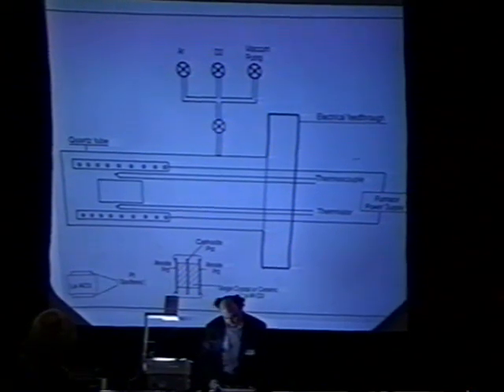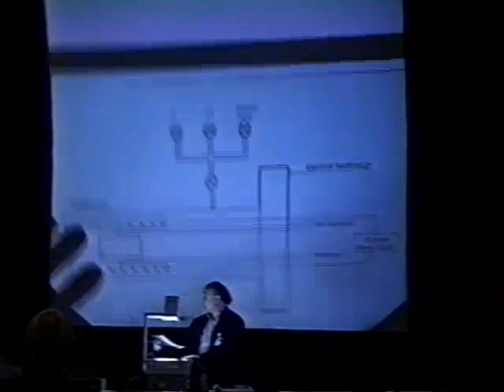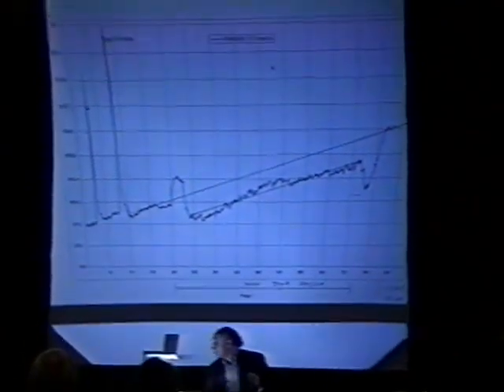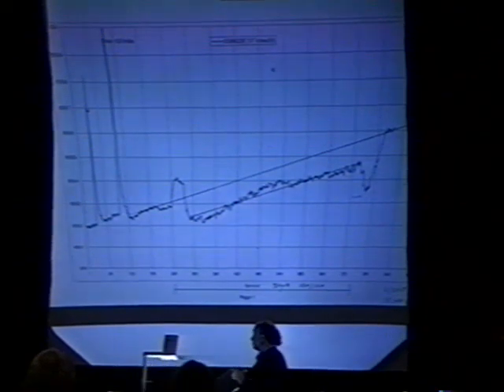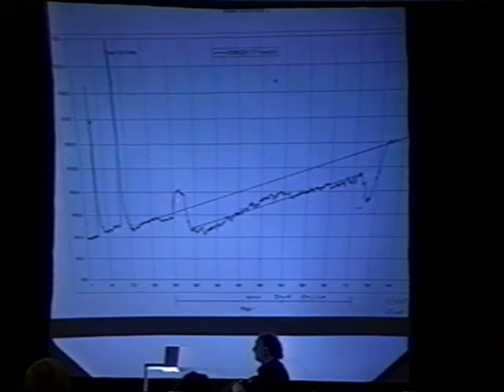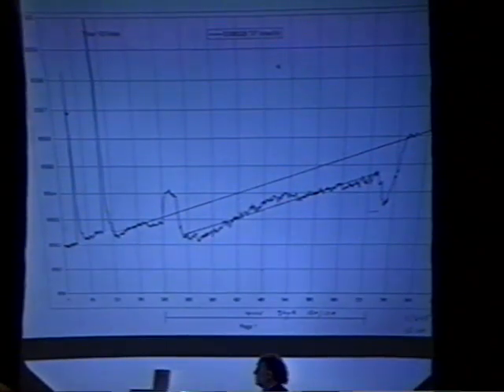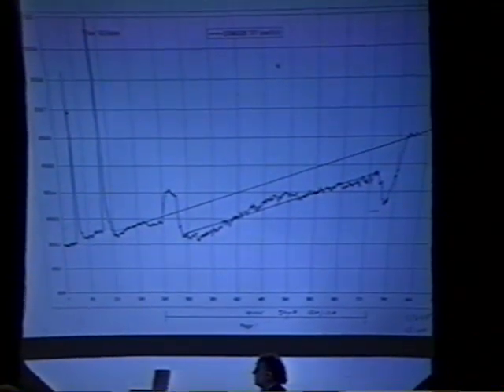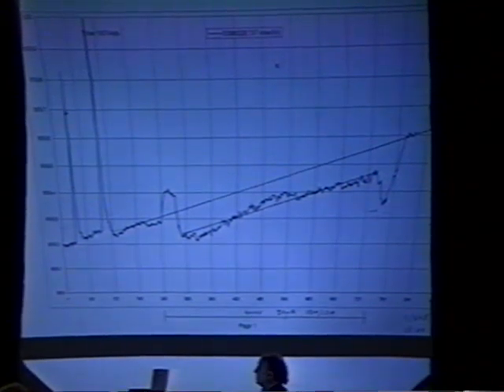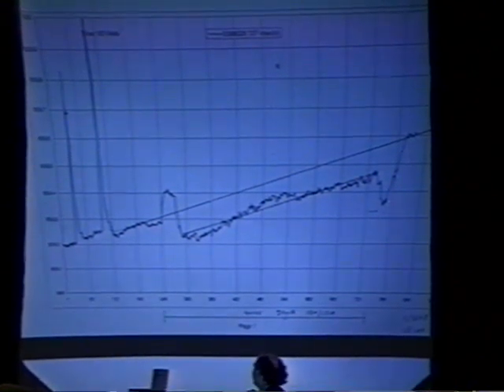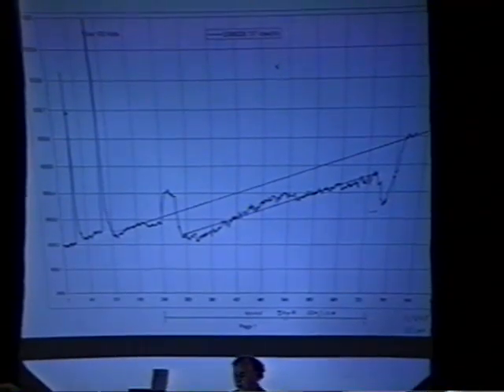And the proof is that when we put in this DC current, we really see first a temperature rise. The temperature rise indicates that the system is responding correctly. And the rise we obtain corresponds to the exact joules we are putting in the system. But there's no change in the gas pressure then? No, this is very, very low. You're talking about 1/10 of a degree at 600 degrees, so very low.